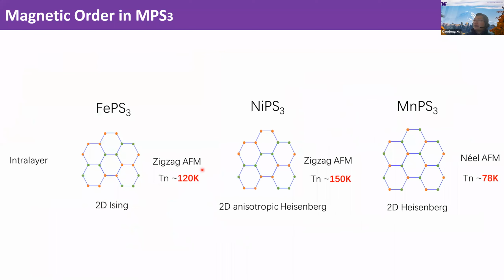This is just a brief summary of these three materials. I'm going to mainly talk about nickel phosphotrisulfide in this talk, but we'll briefly mention iron phosphotrisulfide and also manganese phosphotrisulfide. Nickel phosphotrisulfide is a 2D anisotropic Heisenberg magnet. For iron phosphotrisulfide, actually it's an Ising order with a Néel temperature of 120 kelvins. And for manganese phosphotrisulfide, it's a Néel order that can be described by 2D Heisenberg spin interactions, with a Néel temperature of about 78 kelvins.